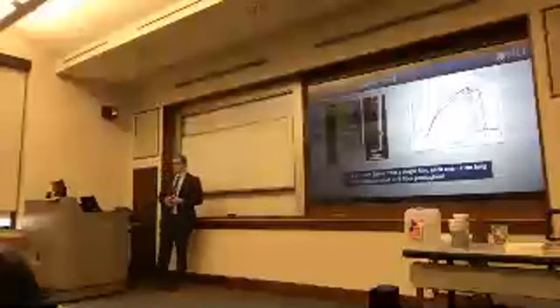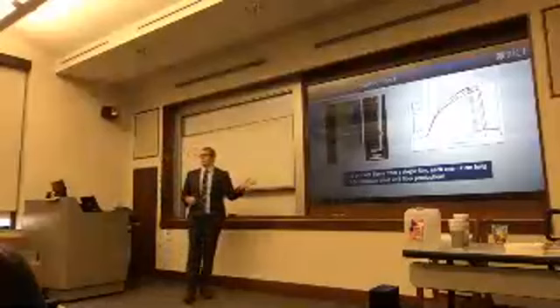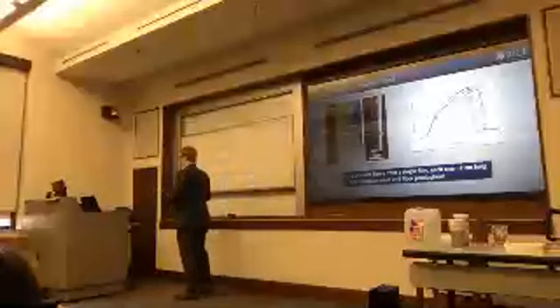So from a single film, we can peel 10 or more fibers. Each one is about 7 centimeters long. So this is really awesome. This allows us now to produce carbon nanotube fibers at the sub-milligram scale, whereas with the full-scale solution spinning method, you needed 175 milligrams. So we've reduced the mass requirements by quite a lot.